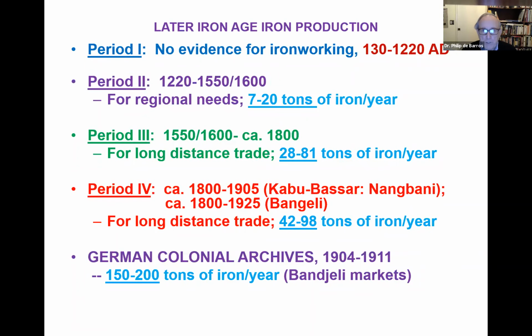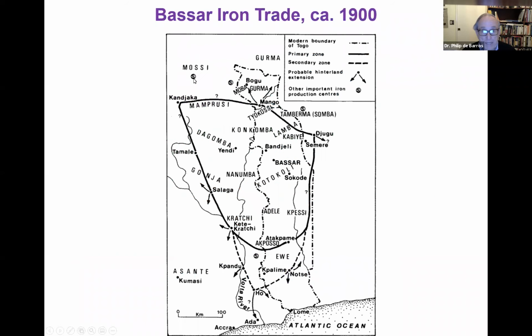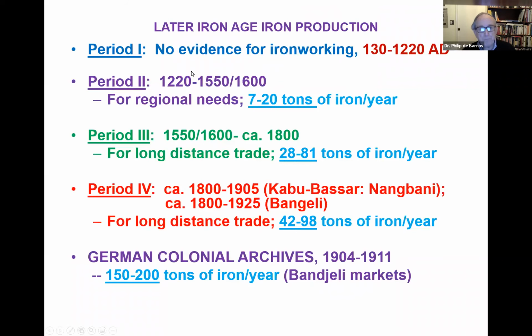Now, my dissertation showed, and further work, that between the early Iron Age and the later Iron Age, from 130 to 1220 AD, there is no evidence of any ironworking, smelting, or smithing. Apparently, there were important population movements, and the metallurgists went elsewhere. We may never know why that's the case, but it is a huge gap. But beginning at about 1220 to 1550, 1600, iron was being produced.